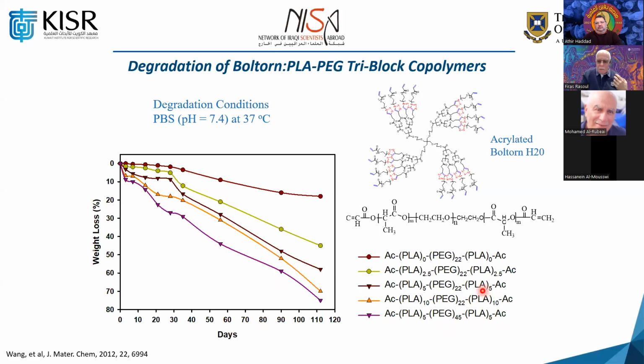So if you look at, for example, the one with the 5, it is this one, okay? It's degrading, almost losing 60% of its weight within probably around 100 days, which is pretty acceptable. While you find these two are relatively faster, losing almost 80% of their original weight. And if you see the last one, we made another composition with much longer polyethylene glycol with 5. You see the impact of polyethylene glycol because it makes it more hydrophilic. It takes a lot of water. If it takes a lot of water, it increases the hydrolysis of PLA. So this is why. But we found this one is probably the ideal according to the requirement by our friend the dentist.